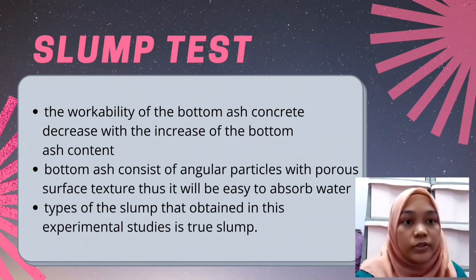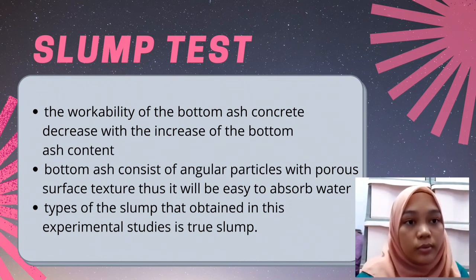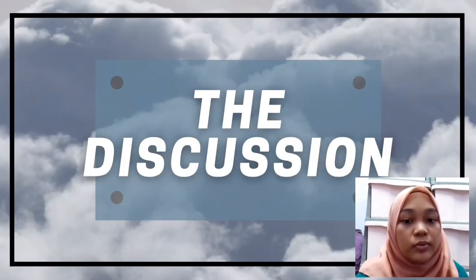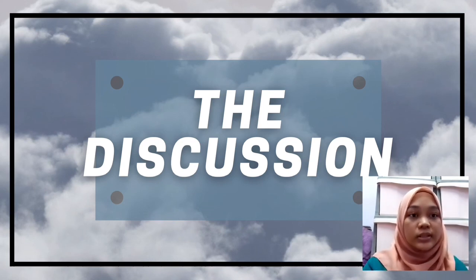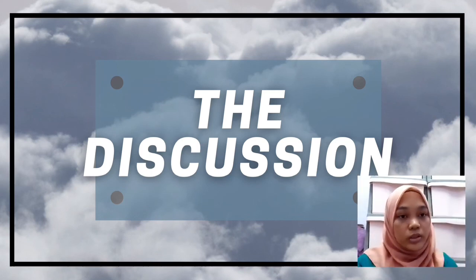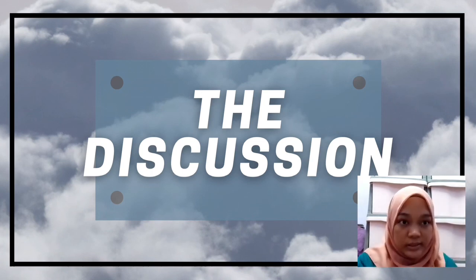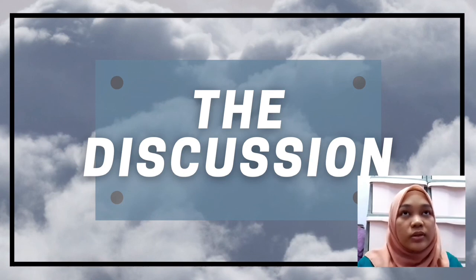Moreover, the workability of fresh concrete that contains bottom ash shows a lower value due to the higher amount of replacement, which requires huge amounts of water and affects the workability. So it shows that the porosity and irregular shape of the coal bottom ash particles can influence the workability of the mixed concrete. What I can conclude based on the result is that workability is an important physical parameter that should be observed because it will affect the strength and durability of the concrete, as well as the appearance of the concrete. It must be measured in order to ensure good quality concrete.